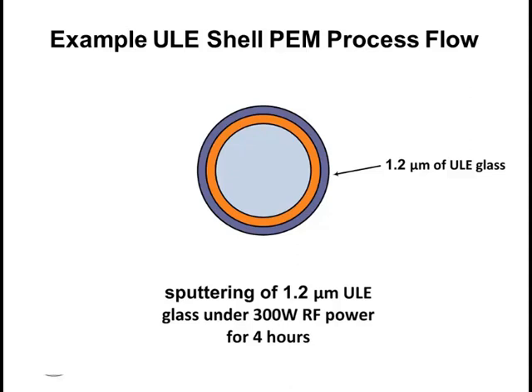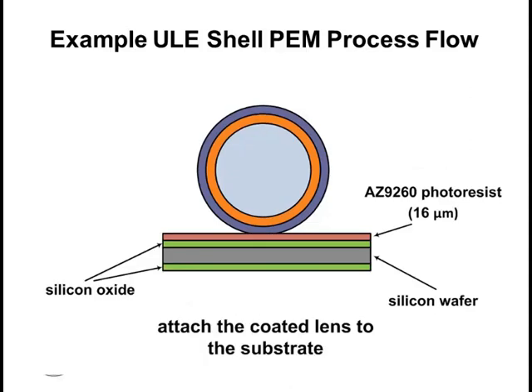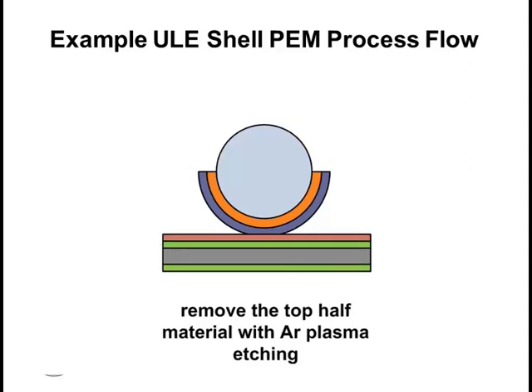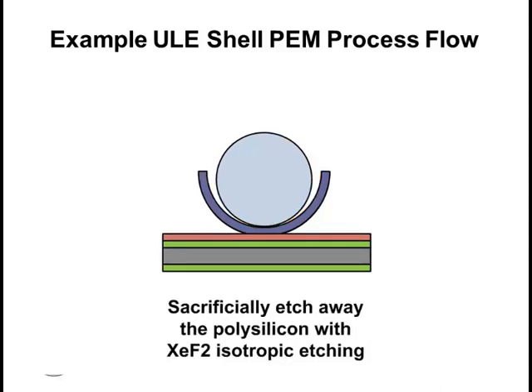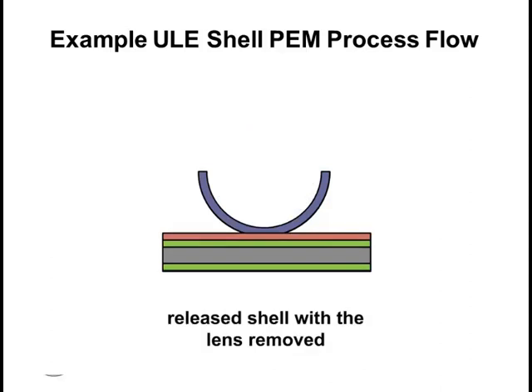But again, using the same technique, you can deposit these 2 layers, and then you can immobilize the mold. This is in case it has no post. In that case, we immobilize it with photoresist on top of an oxidized wafer. The next thing we do is etch the top, via ion milling, straight ion milling with argon, and we remove the top half of the sphere, the sacrificial layer as well as the structural layer. Actually, this cartoon is not accurate; you indeed get more vertical sidewalls here. After this step, the sacrificial layer, which is polysilicon, has been exposed, so we can remove it with xenon difluoride, and that releases the mold, so we can remove it later by flipping the structure and end up with your shell.